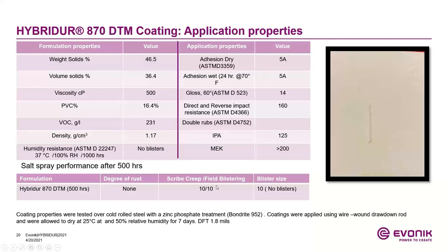It's got both scribe creep and field blistering ratings of 10 over 10, which is the best rating you can get, and absolutely no blisters either in the field or on the scribe. Again, outstanding adhesion properties, both wet and dry adhesion, gives a rating of 5A, with a greater impact resistance, again about 160, with an excellent rub resistance of greater than 200.